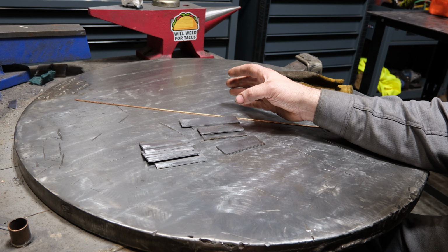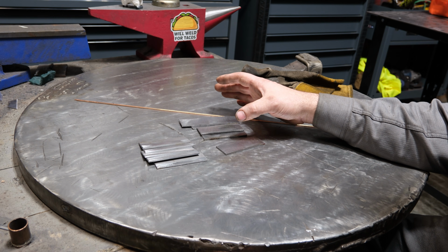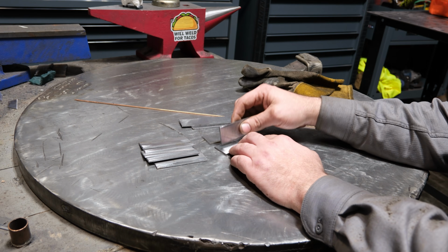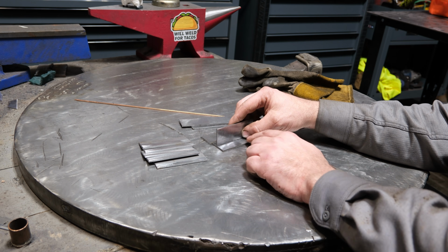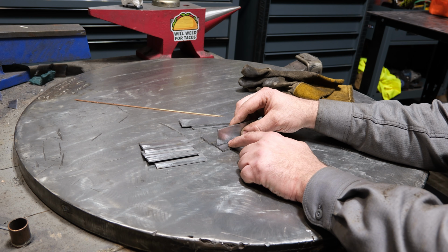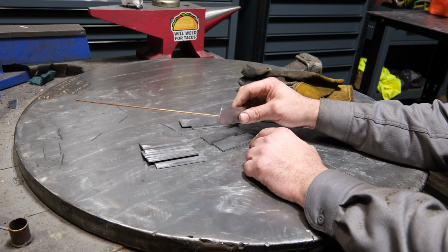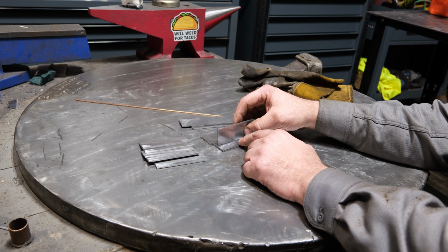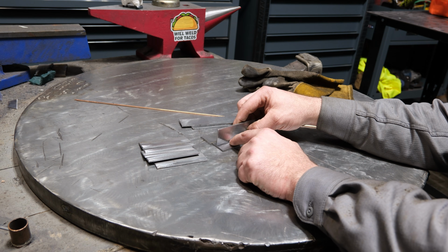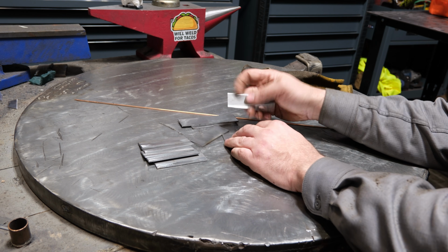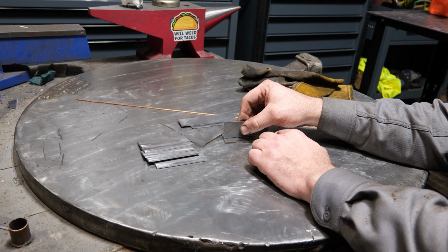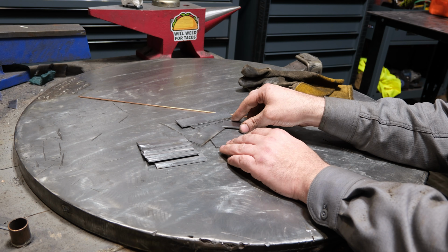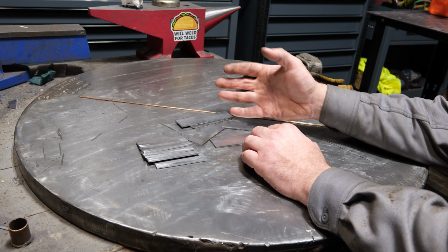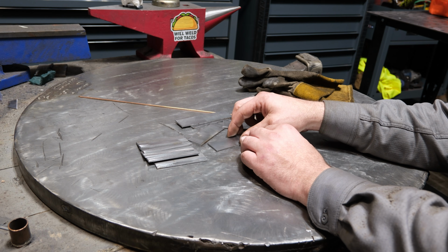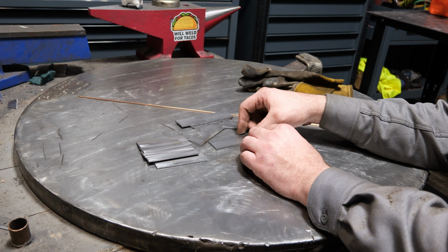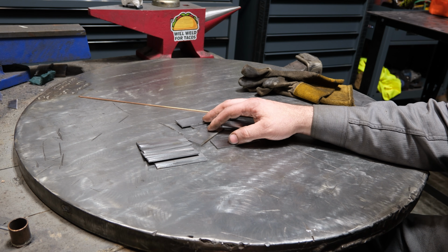If you have thinner stuff, that's all right. If you have thicker stuff, that's perfectly fine as well. I find that 1/8 or 3.2 mm works really good because you can put a lot of heat into this stuff and you don't melt through, so it's not as frustrating as, say, 1/16 or 1.5, 1.6 mm plates. So you can put more heat into it, and when you weld one side, you can oftentimes go back and with minimal prep, weld the other side. When you get into thinner material, you're going to have melt through, and if you attempt to weld over that due to the scale, you're just going to end up getting a terrible looking weld and probably porosity. So this material or thicker generally works pretty good.